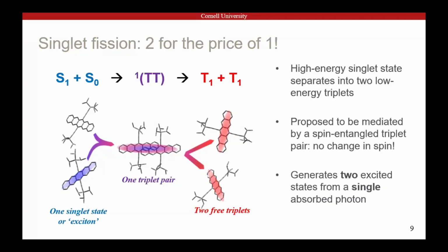So the magic of this process that lets it happen is this intermediate state that we call 1TT, the triplet pair state. At first, this was just kind of a mathematical construct. We realized about a decade ago that it's a real intermediate state we can see and touch and do things with. And roughly, you can conceptualize it as 2 triplets next to each other that are pointing in opposite directions. And because their spins cancel out, you go from a spin 0 state, the singlet, to this coupled triplet state where the spin is still 0, even though it's built of higher spin triplets. And then they separate on some longer time scale. So there's no change in spin in this process, which means as long as you conserve energy, it can be very fast and very efficient.